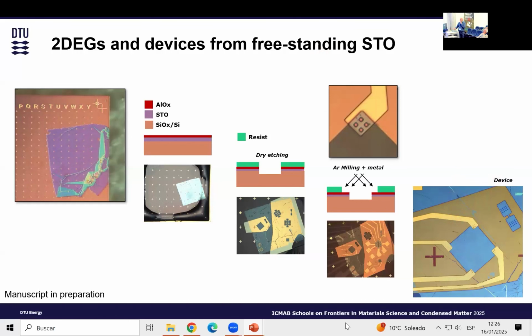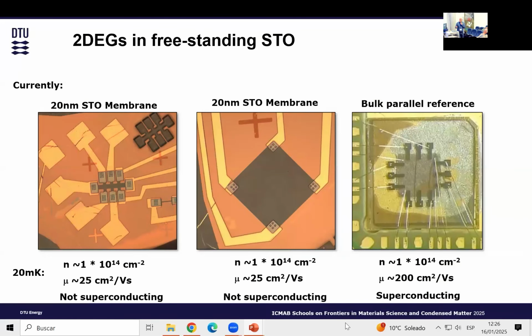This is a Van der Pauw device that we did. What we further did is we took this device and made another device, which is a Hall bar device, and we compared it also with the bulk. So we did another sample, which is directly grown on the bulk. We put aluminum on the bulk, we etch it, we reduce it, and we got the 2DEG as you expect. The interesting, or the challenging thing here, I would say, is that the carrier density turned out to be almost the same. The mobility, you can see, is lower compared to the bulk reference.